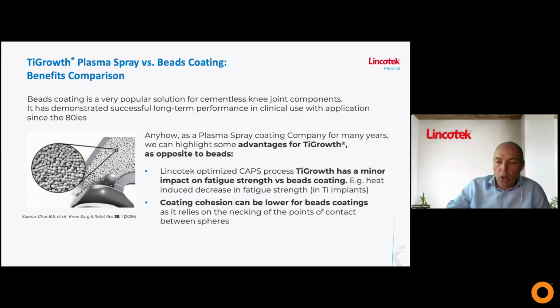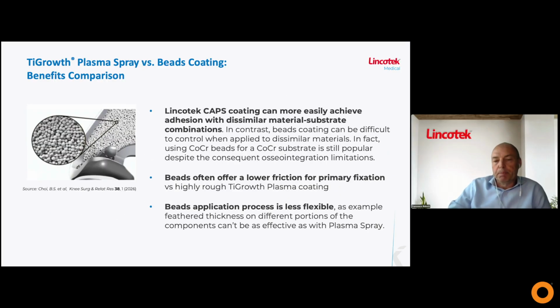Coating cohesion can be lower for bead coatings when compared to plasma spray coatings, because it relies on the necking of the point of contact between spheres. And the plasma spray coating has a tremendous advantage when it comes to adhesion on dissimilar materials. So we can apply the TiGrowth coating, the titanium coating, on cobalt chrome. Whereas with beads, very often it relies on applying cobalt chrome beads, so with some limitation regarding the osseointegration. So potentially further coatings like hydroxyapatite are needed on the cobalt chrome beads. So it's much more straightforward to apply the titanium plasma spray coating directly on cobalt chrome.